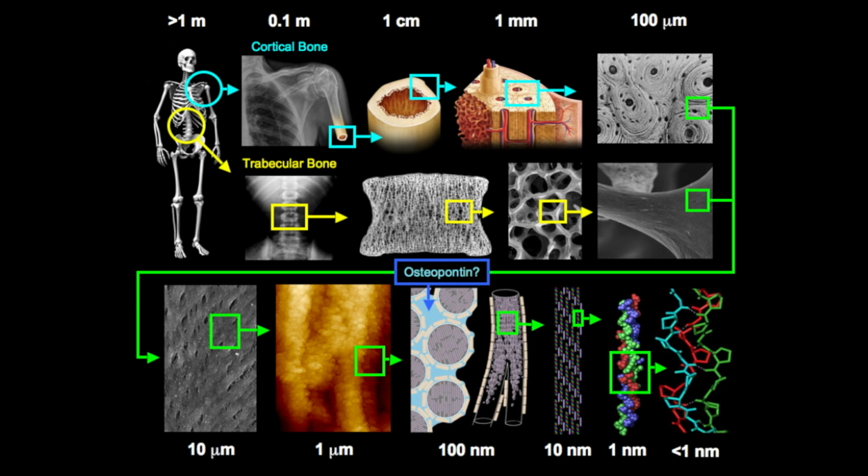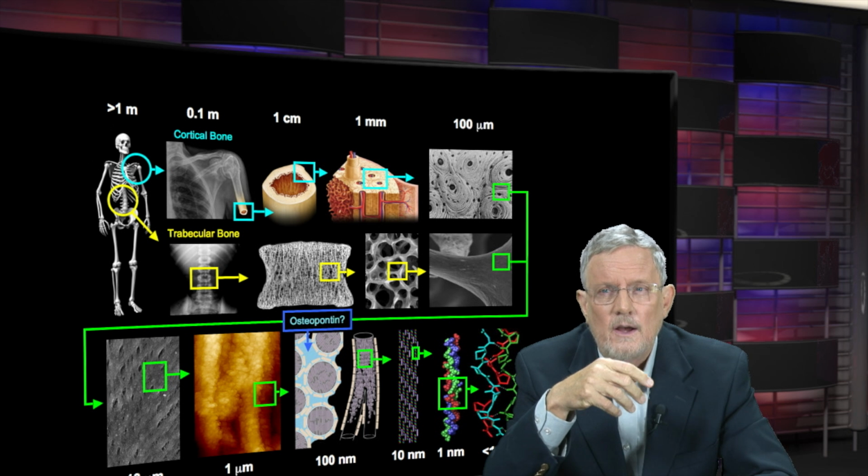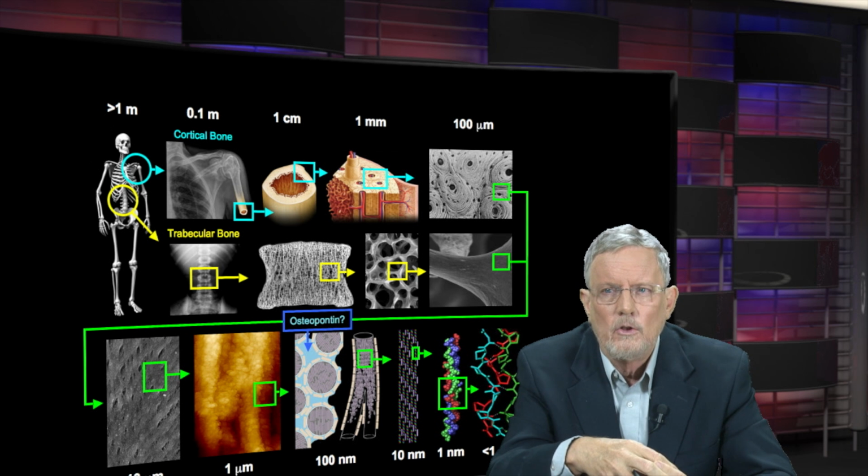What you see there at the 1 micron scale is a picture of these mineralized collagen fibrils that you saw on the Physics Today cover, sticking together. In the next frame, you see what you would imagine. These are more or less rounded fibrils, so imagine what the cross-section would look like. You see the rounded fibrils coated with the mineral plates, and in between them there's something. What is that? It's a liquid gel. Your bone has these fibrils inside a liquid gel, and it's the liquid gel that holds them together.